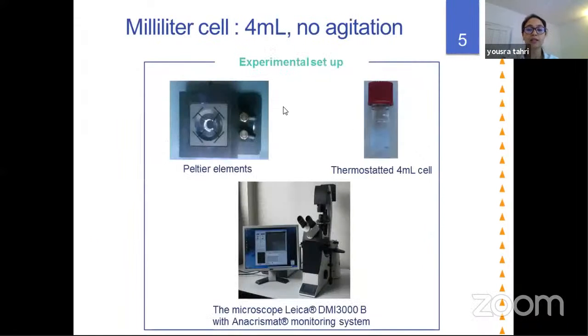Then we investigated the crystallization of L-glutamic acid in a thermostated 4 milliliter cell without agitation. We controlled the temperature of this cell using Peltier elements. The cell and the Peltier elements were put under a microscope that was equipped with a camera, and we could take pictures of the crystals every 10 seconds to see what happened during the different crystallization experiments.